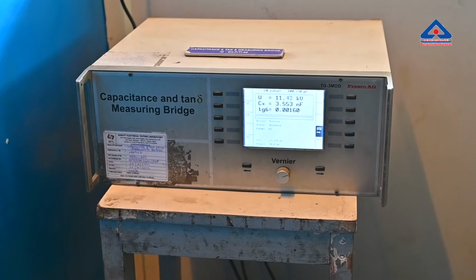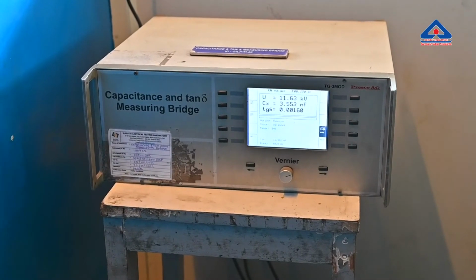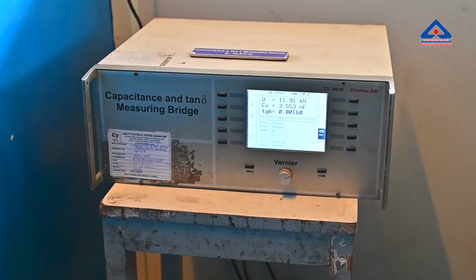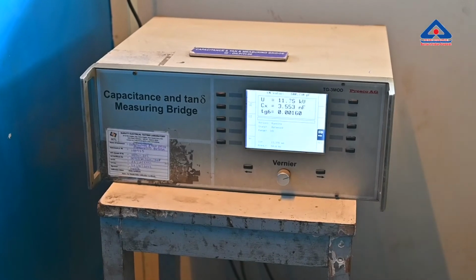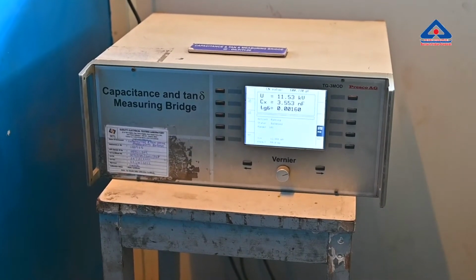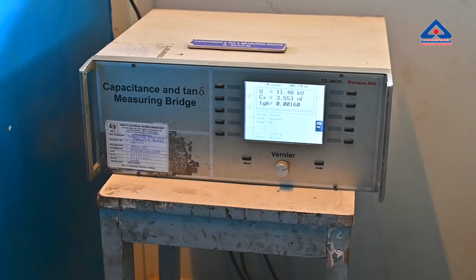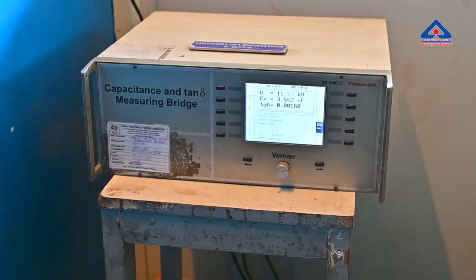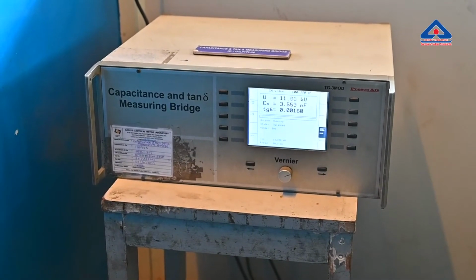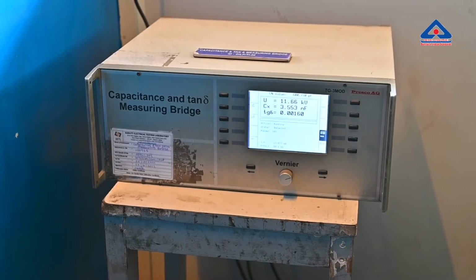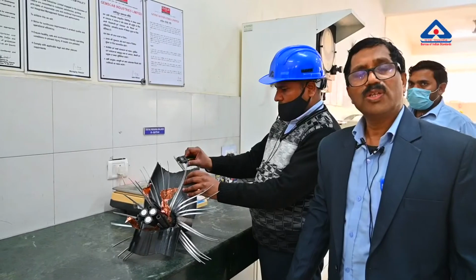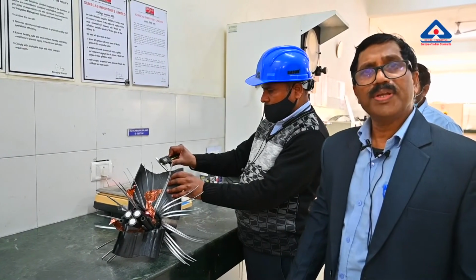We are going to measure the dielectric power factor as a function of voltage. This is 11 kV cable, so at 11 kV we are measuring the value. It is coming 0.00160 against the requirement of 0.0020 max. This is a 3 core 240 square mm 11 kV cable.